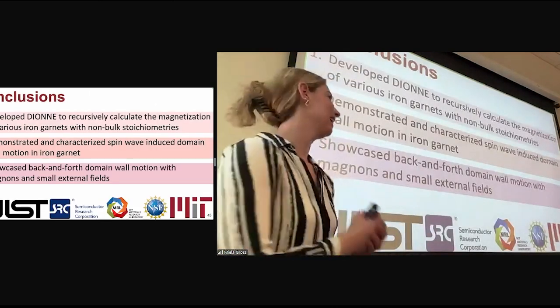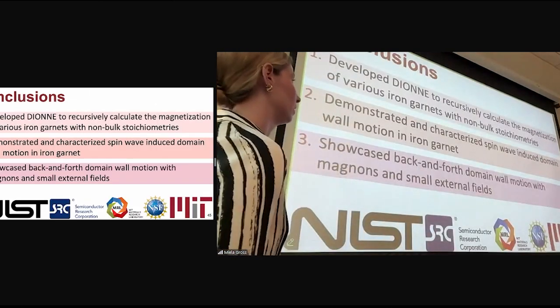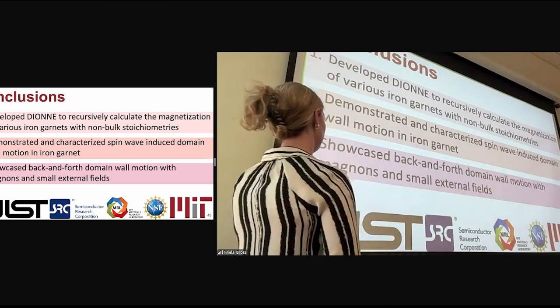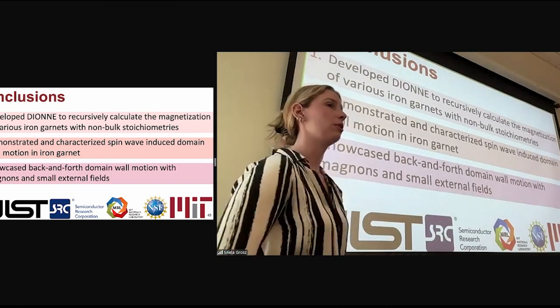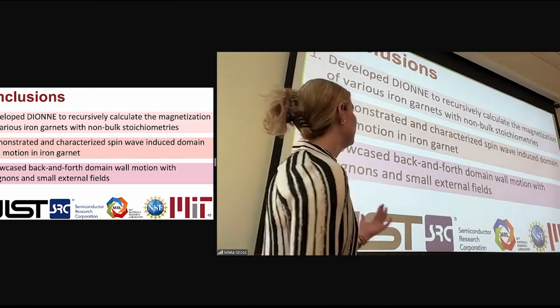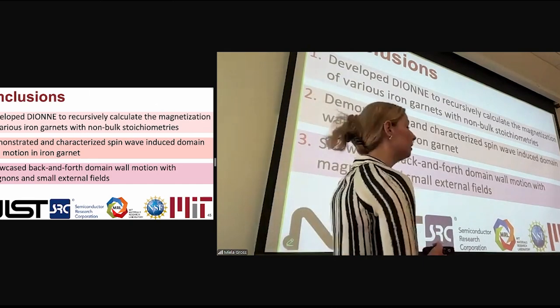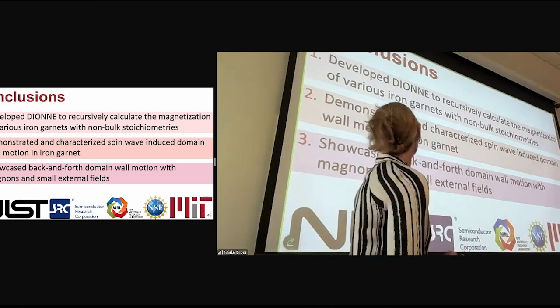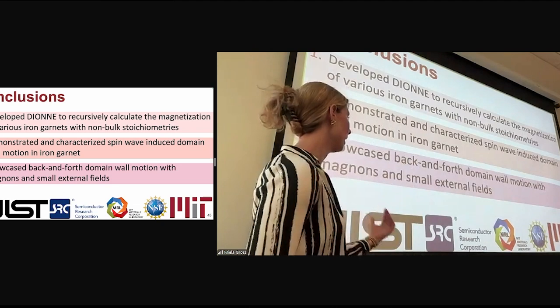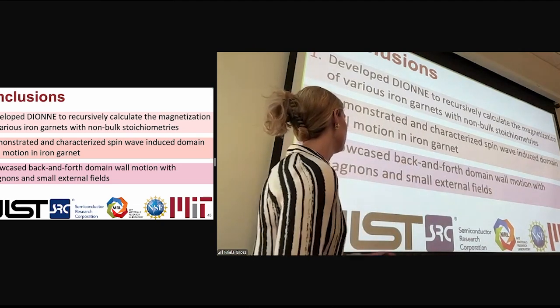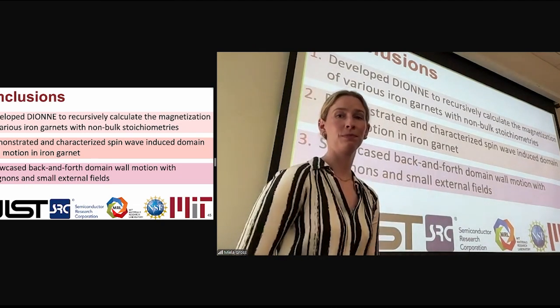So in summary, I have developed DIONNE, which recursively calculates the magnetization of various iron garnets with non-bulk stoichiometries. I've demonstrated and characterized spin wave-induced domain wall motion in iron garnet, and used that knowledge to showcase back and forth domain wall motion with magnons and small external fields.